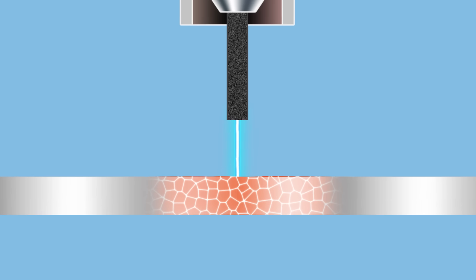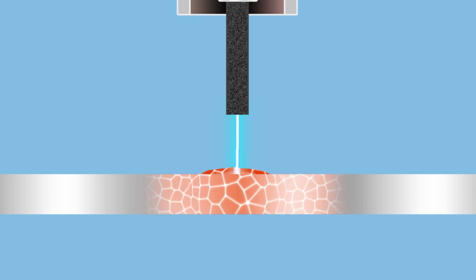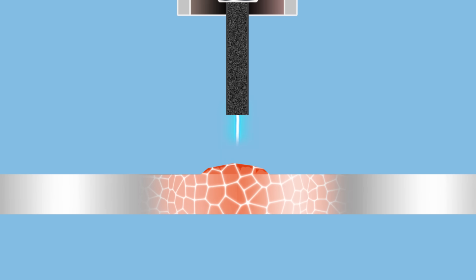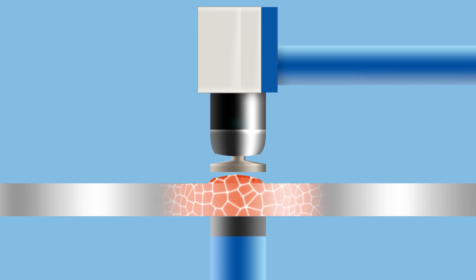However, when Starship is welded, the heat causes the metal in that area to soften up again. This is where SpaceX's giant planishing machine comes in. Planishing involves hammering the welds down and compressing them until they match the hardness of the surrounding metal. This has the added benefit of smoothing the finish of the welds and improving their look.